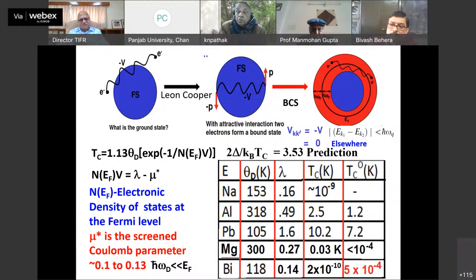For sodium, we know the Θ_D, we know the electron-phonon coupling constant. You see that you get a temperature like 1 nanokelvin. For aluminium, the calculated temperature is 2.5, whereas the measured one is 1.2. And lead is 10.2 and 7.2. Magnesium, it's predicted to be 30 millikelvin. Unfortunately, it's not superconducting at 100 microkelvin.